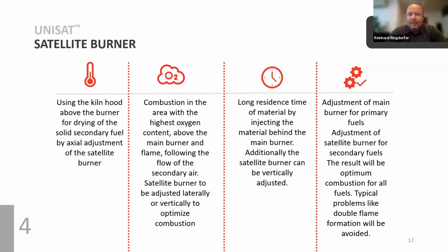And we started to do our first tests. And there are some obvious advantages compared to firing through the kiln burner, which is first of all the location of the satellite burner, which means you have a high amount of oxygen available, and you have a very high temperature coming from the secondary air. So when injecting the material, you start the process that we heard before. So you start the drying, you start the devolatilization, everything still before the particles reach the main flame.